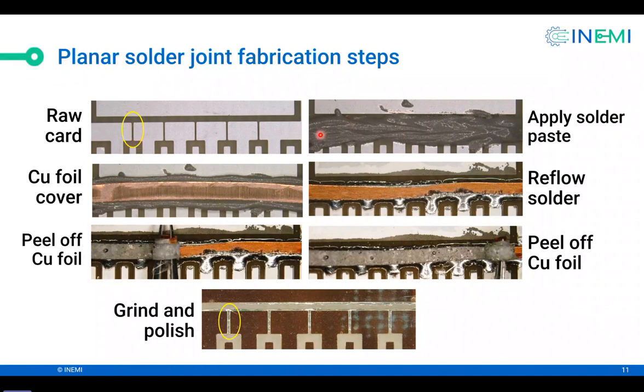So first thing we do is we paint solder paste over this region, and then we lay a 5 mil, 0.005 inch, foil of copper. Now the reason this foil is curved is because when you shear the foil, it's hard to keep it straight, but we try to keep it as straight as we can. But that's okay as long as it covers these gaps. And then in the next step, we reflow the solder, in this case at 180 degrees centigrade for about 12 minutes.